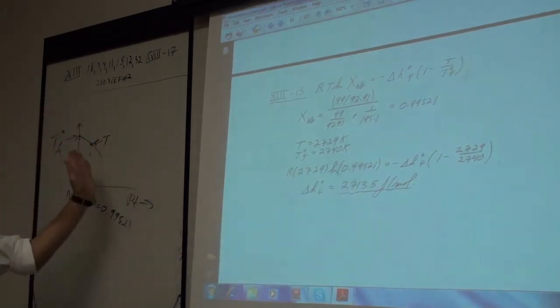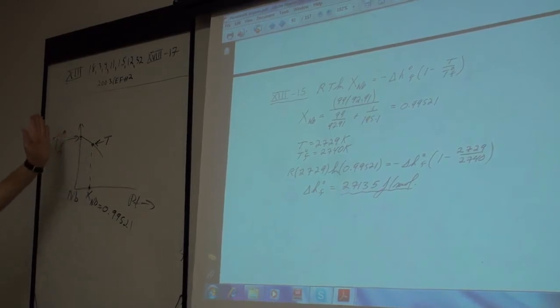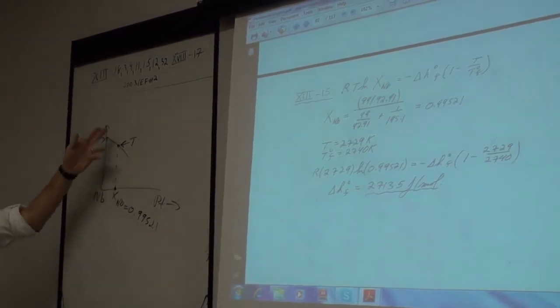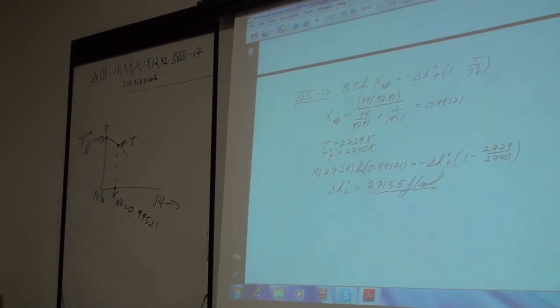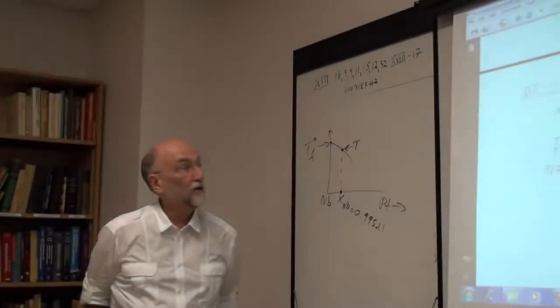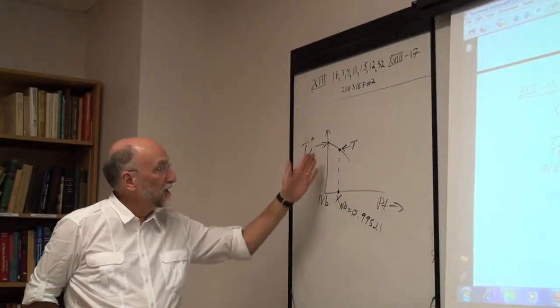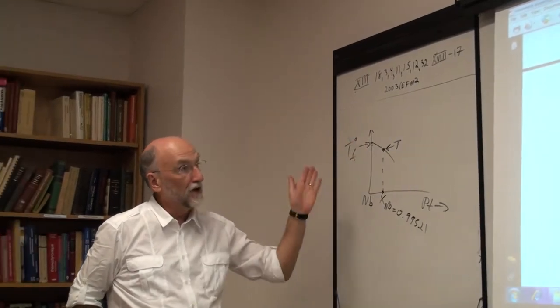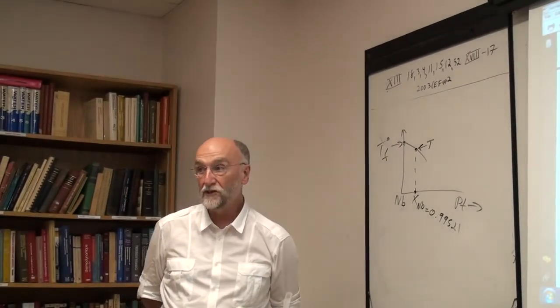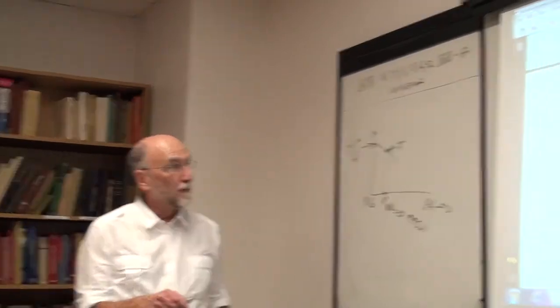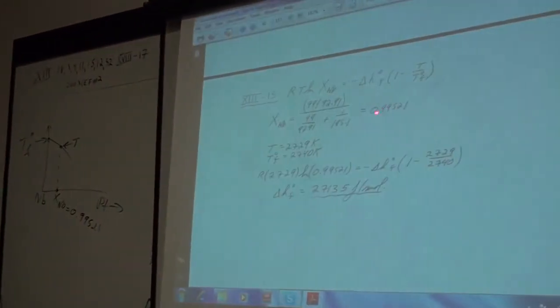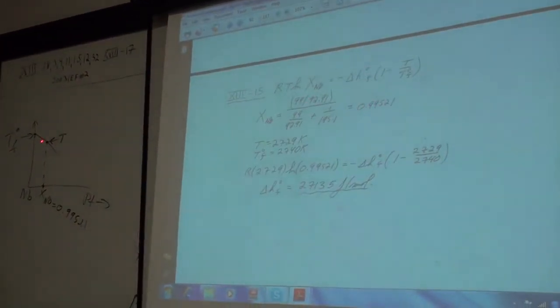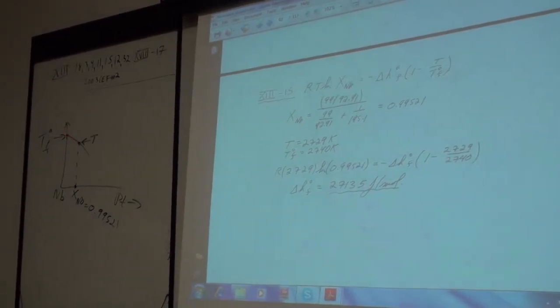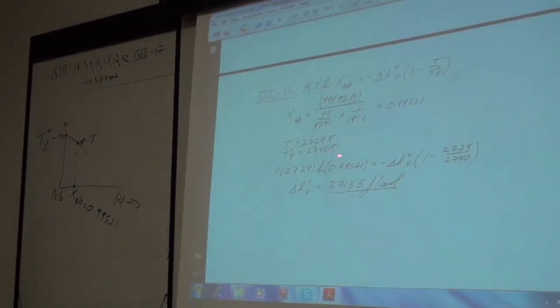But this is always true if you're in a very rich solution, very, very dilute in platinum, because Raoult's law always applies as you go to the limit. So as you go to the limit of pure material, the activity of the solvent always approaches the mole fraction of the solvent, Raoult's law. And at less than 1%, a half a mole percent is probably pretty close to the limit here. So we're making the assumption of an ideal solution, but it's a good assumption because you're in the limiting region.